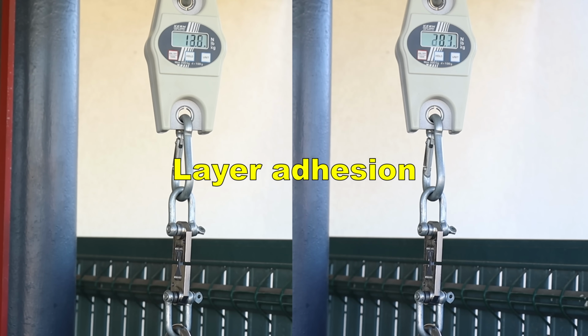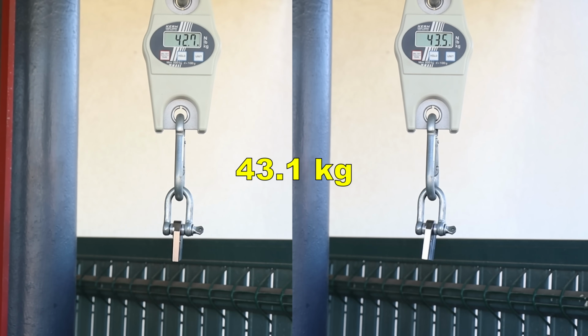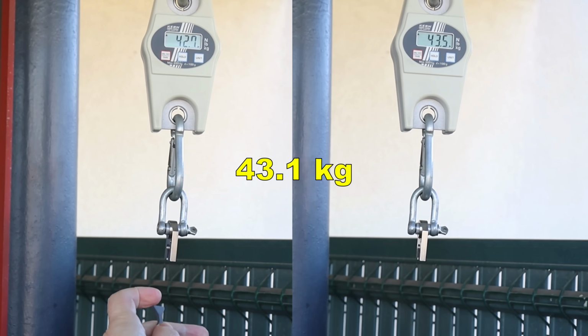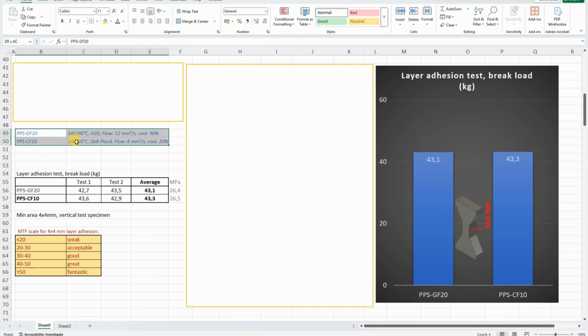Layer adhesion with vertically printed parts. Now, even if the print temperatures are similar, the part cooling, the flow, and even the layer printing time is quite different, but even then, these numbers are extremely similar. And this is a great layer adhesion. Here you can see my rating for this test object.